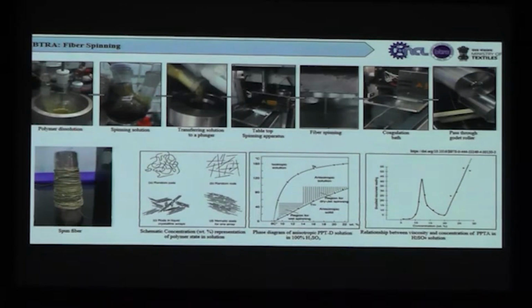The facilities that handle it also have to be of a grade which can handle sulfuric acid, like Hastelloy or steel of a particular grade. Here is our first or second attempt where we could dissolve the polymer at this concentration, about 19 weight percent, which means it has formed the lyotropic phase, like rods going down a stream which are aligned in one direction. Then it helps dissolve and then form a fiber.